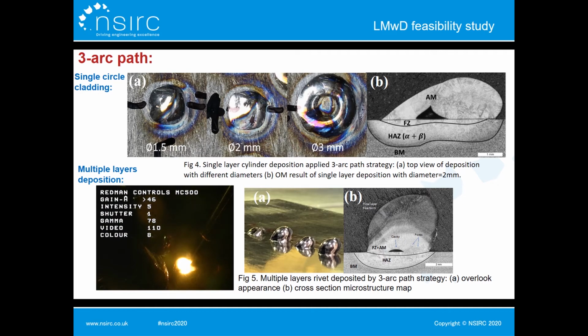Similar problems also appear in the multiple layers deposition in figure 5. Although it can successfully build up the cylinder rivet, the cavity and the deposition angle issues still exist. So after adjustments in the full circle strategy, the material input will cover all the paths, and an extra wash path is also added to fix the current issues.